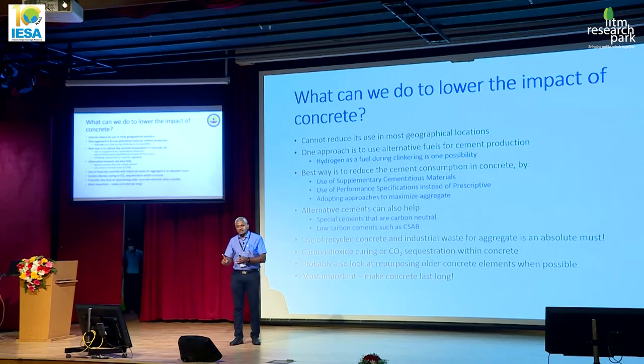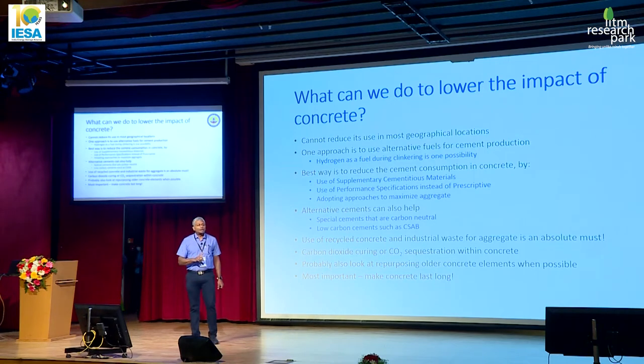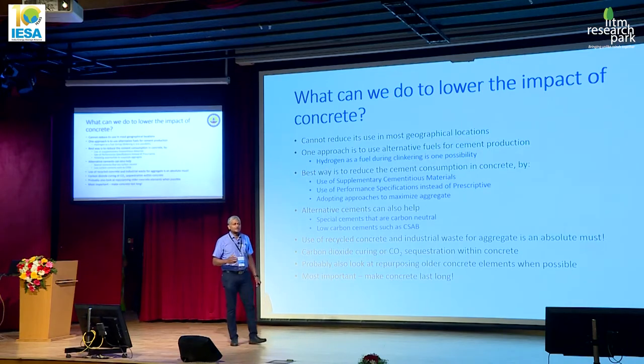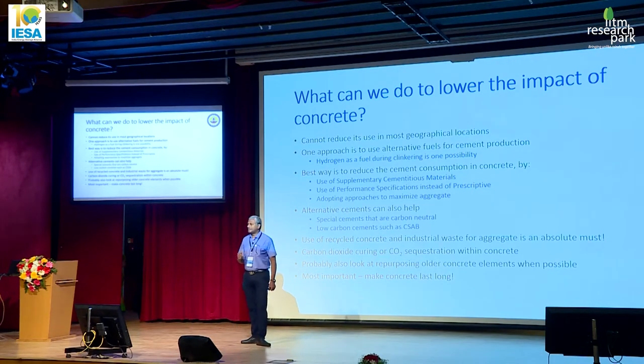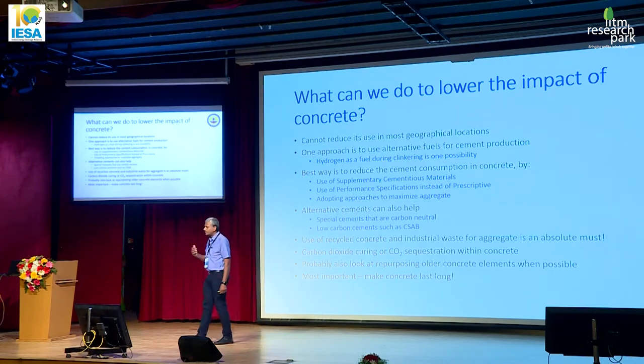Of course, this 1 ton is not exactly from the stoichiometry. Some of it comes because of the burning. We use fossil fuels to burn, and that also releases some CO2. So overall impact is about 1 ton of CO2 per ton of clinker that is produced. Now, one way to reduce that is to use an alternative fuel. Alternative fuels that don't have that much impact on the released CO2.